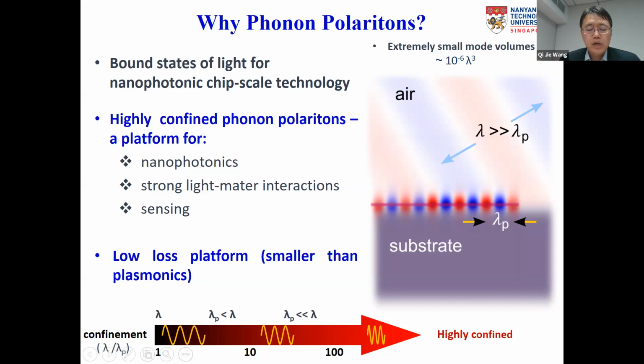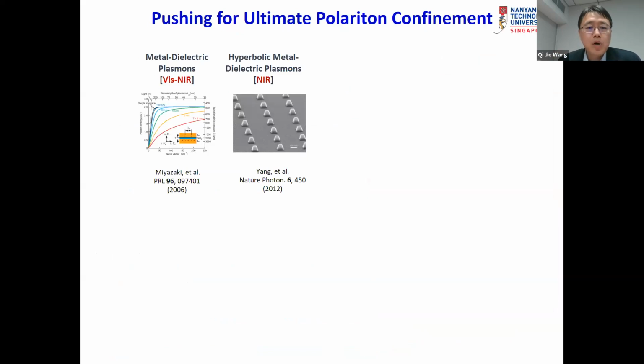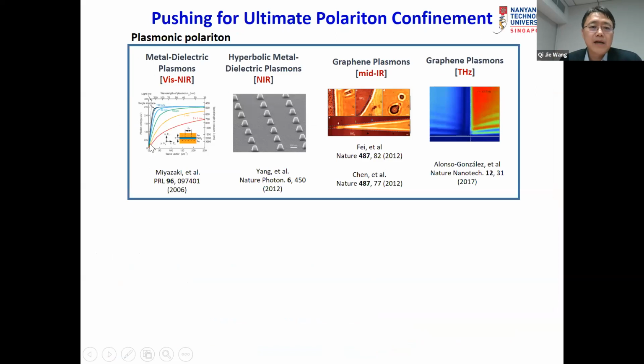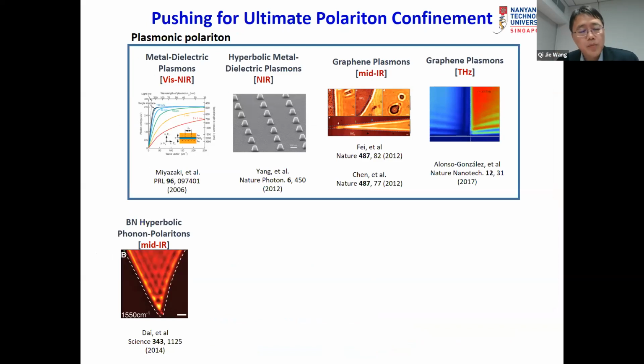So here we want to highlight that the highly confined regime we are talking about means a confinement of around 100. Okay, so that's our interest. And phonon-polaritons, because of their relatively long lifetime compared to plasmonics, also have relatively low loss, providing a low-loss platform for nanophotonics. In the past, polaritons have been well studied in plasmonic platforms: metal-dielectric plasmons, hyperbolic metal-dielectric plasmons, and graphene plasmons, recently in both the mid-infrared and terahertz regions. In the phonon-polariton platform, boron nitride hyperbolic material has been widely studied for achieving highly confined phonon-polaritons in bulk boron nitride.